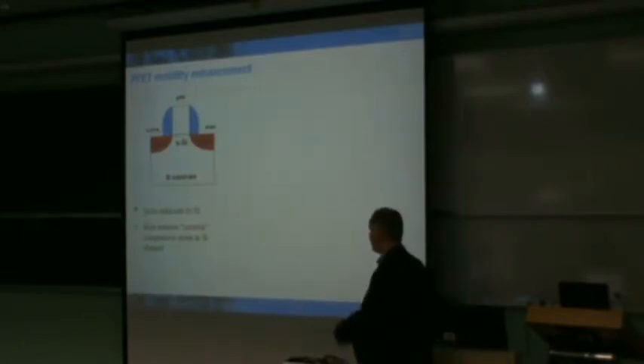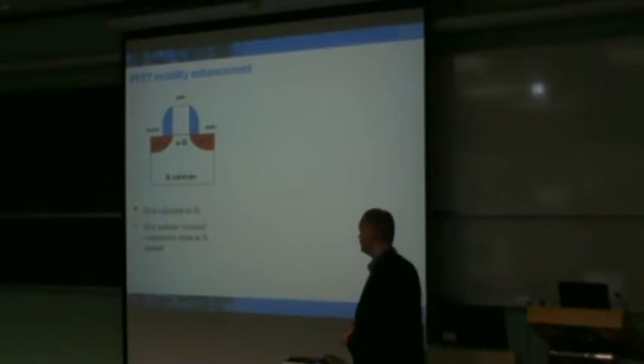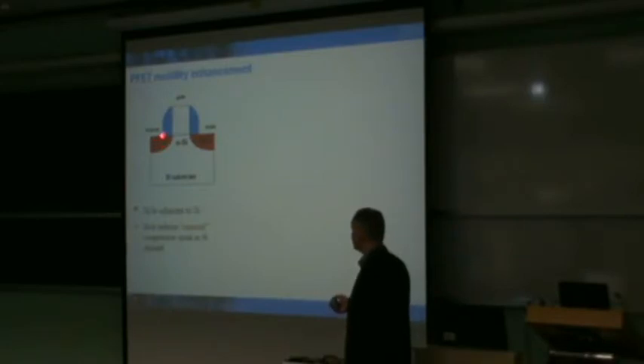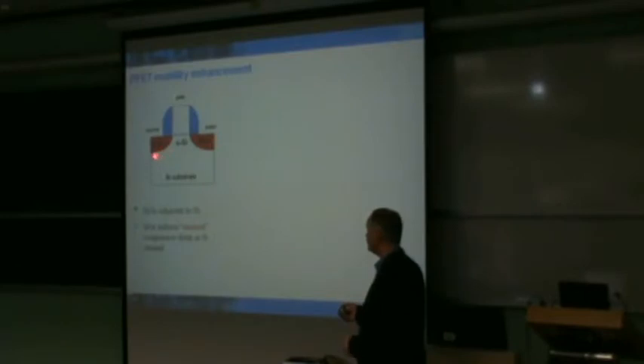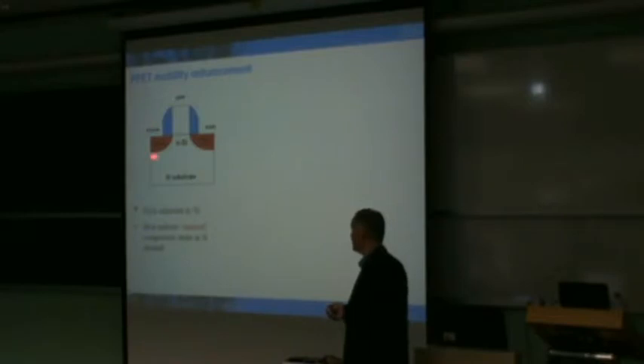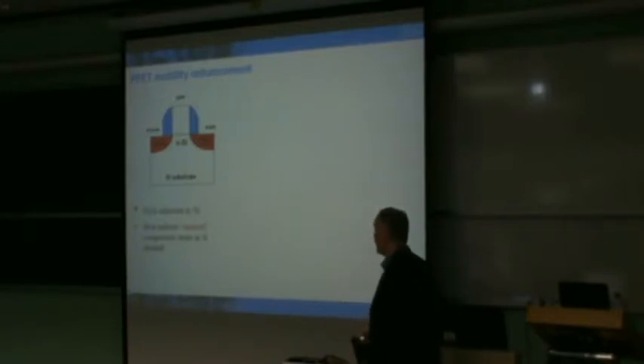Now, the complementary structure is based on a P-type field effect transistor. And the structure that has really shown the most benefit in that has been the incorporation of stressor structures that are embedded within the silicon. So basically the silicon is recessed, etched out of a certain region. It's cleaned, and then a material is deposited in the source and drain regions. In this case, again, the silicon germanium is used. And that induces a change in the lattice constant here in the channel region.